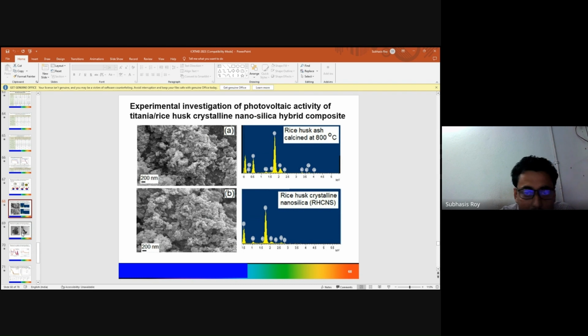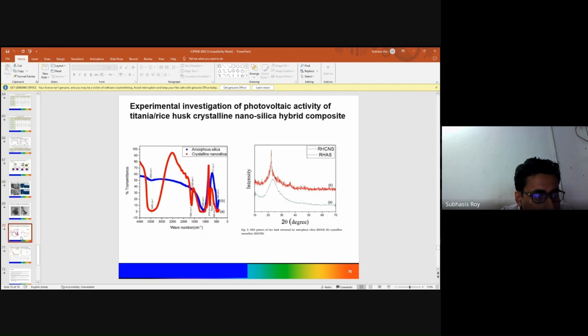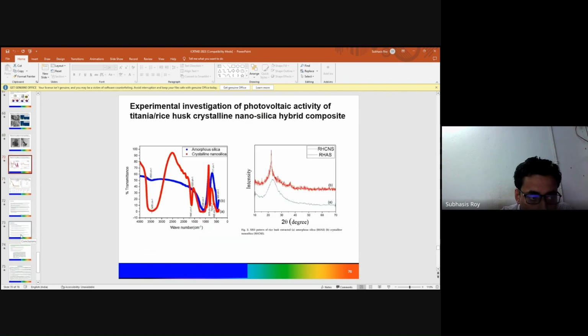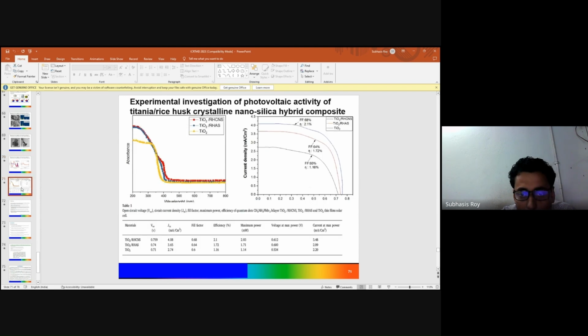Yeah, this rice husk nanosilica we applied in the solar cell. We did all the optical properties, absorption properties. Finally, these are the current-voltage, optical and electrical properties. It is showing a maximum efficiency of around 2.1 percent in the case of the rice husk related nanosilica.